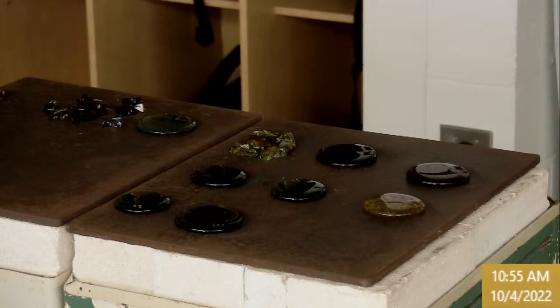The proportion of cullet in glass can be as high as 90%. Cullet melts at a lower temperature, so for every 10% of cullet in the mix, the factory uses up to 2.5% less energy to produce its glass. Now that is a clear incentive to recycle.